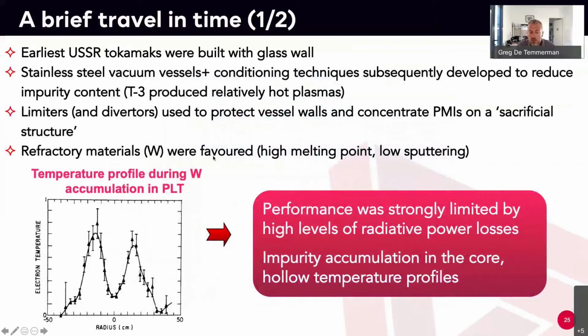And then it became used quite a lot, but there was already an issue very easily found: tungsten is very heavy. It has a lot of electrons, so when it penetrates inside the plasma, it radiates a lot of the energy. What they noticed at the time, I was not born, is that the plasma was actually cooled down to extremely low temperature inside the core, and basically fusion would never happen like that. So tungsten was resistant, but we could not make it work in that way.